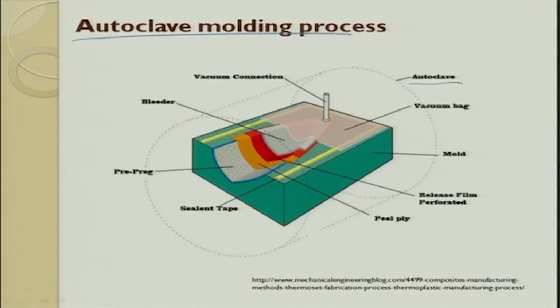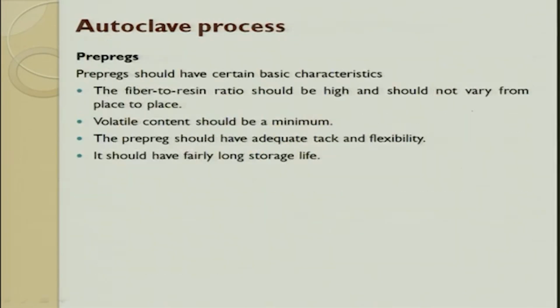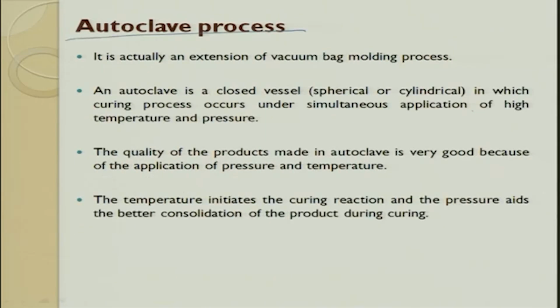You can also have a positive mold, in the sense, if you want a component which is made like a U, an inverted U, then your mold becomes something like this, and then you repeat all the process. That means a prepreg is placed, a bleeder is placed, a peel ply is placed, a releasing agent is there, the mold becomes a positive mold, and you can put a vacuum so that you get the required output. So now let's go into the process and understand a little bit of the process.